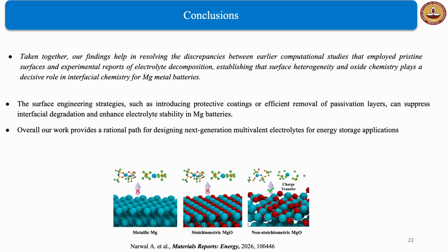Taken together, our findings help in resolving discrepancies between earlier computational studies that employed pristine surfaces and experimental reports of electrolyte decomposition, establishing that surface heterogeneity and oxide chemistry play a decisive role in interfacial chemistry for magnesium metal batteries. Also, our work suggests that surface engineering strategies such as introducing protective coatings or efficient removal of passivation layers can suppress interfacial degradation and enhance electrolyte stability in magnesium metal batteries.